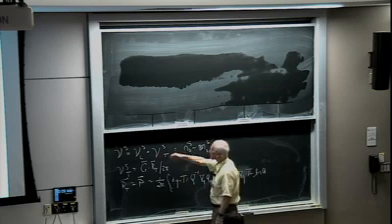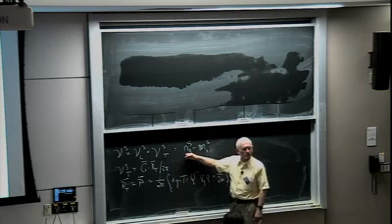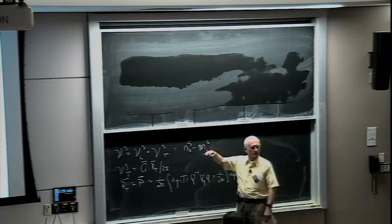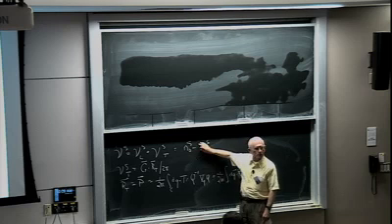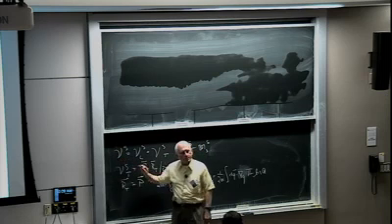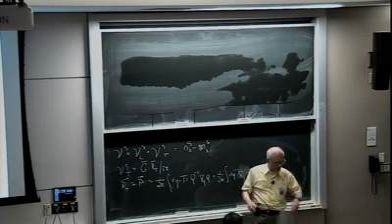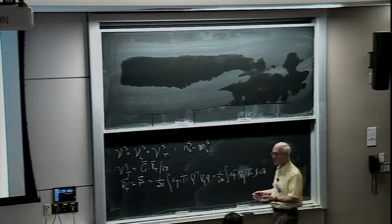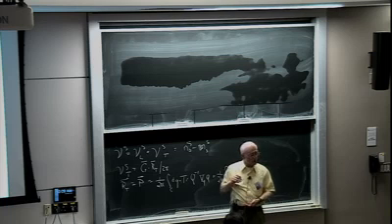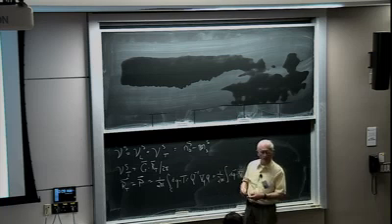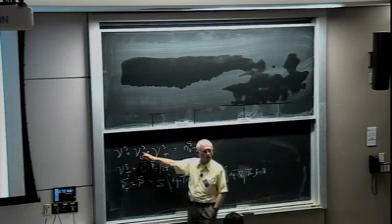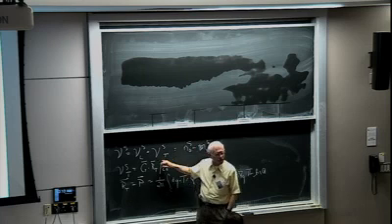And so we want to look at this quantity, which is the number of zero modes on the surface minus the number of states of self-stress. As a practical matter, in all of the examples we're looking at, this is equal to 0. So this is a statement about the number of zero modes on the surface. Now, you might expect that there's a way of dividing this up, at least rationally, into 2 different parts, because we have one part that's telling us that we have to obey the Maxwell count, and another part that has to do with the topology moving one side to the other. So we break it up into what we call a local count and a topological count.